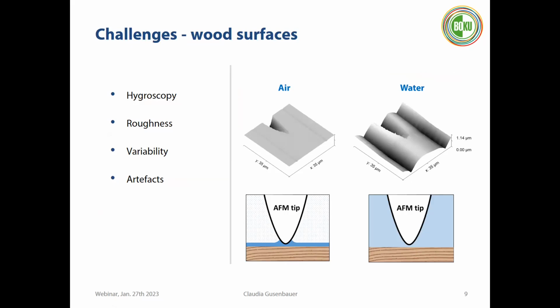So we are able not only to perform measurements in air, but we can also perform measurements in liquid surroundings, which helps us to overcome these capillary forces which we have between the tip in air and our wood sample. You can see this in the middle image on the bottom of the slide. And to overcome these capillary forces, which happen when the AFM tip is touching our wood sample in a standard environment, we can make the whole measurements in a liquid surrounding. So we place the sample inside, for example, water, and then we perform these measurements with an aqueous surrounding.